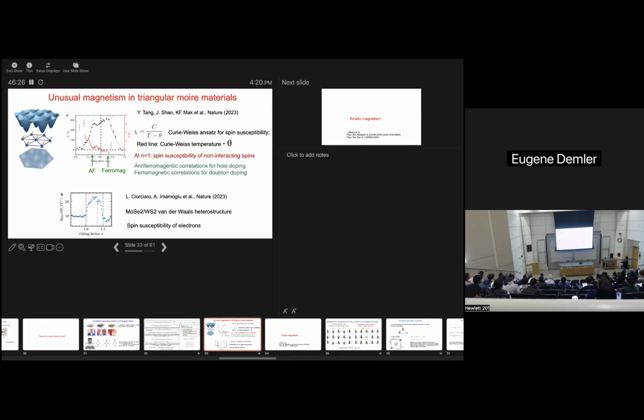But let's go back to just the results for spin susceptibility. The way they present the spin susceptibility is the way one would present spin susceptibility for lattice models. And what's important is this parameter theta. If theta is equal to 0, we have spin susceptibility which is 1 over T, which is just free spins, like non-interacting spins. When theta is positive, we have an enhancement of susceptibility, which indicates ferromagnetic interactions. And if theta is negative, we get suppression of spin susceptibility, which indicates antiferromagnetic interactions.